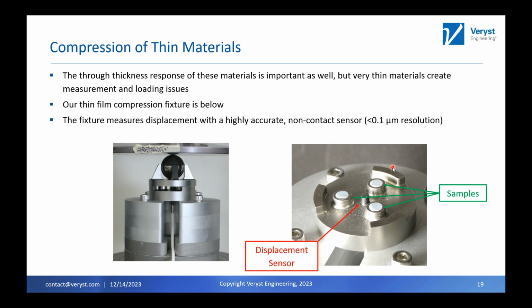Not really. Cyclic tests can be a little harder to control. If you want to hit 5% strain exactly or 10% strain, that can be a little difficult. What we've found more useful in these thin films is that we can control the ADMET in a way that we say move at 0.001 millimeters a second until the force is 1,000 newtons. So we'll go at a displacement rate, but then we stop at a load and then unload to a load and that kind of thing.